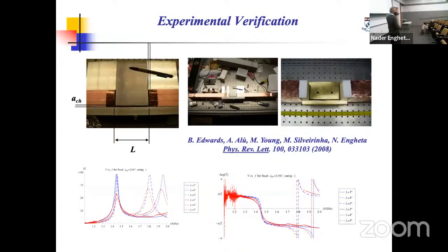So we experiment 2 years after we came up with this theory in 2006, we experimentally verified that in my lab using the microwave setup that you see there. And this microwave setup that you see there, you can actually create a waveguide at cutoff that you see over here and the two other waveguides input output. What you see over here is the magnitude and phase of the transmission coefficient of this. You notice, by the way, that in this setup, we design it such that you can actually change the length of that transition region. And as you change, you notice that this coupling, this super coupling does not change. This is an indication that this is not a standard Fabry-Perot effect. You notice that there are other peaks of transmission that you see over here.